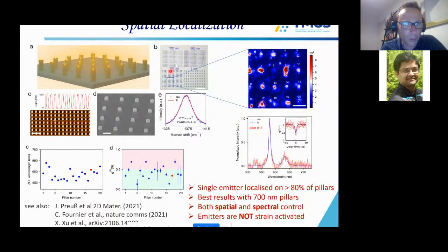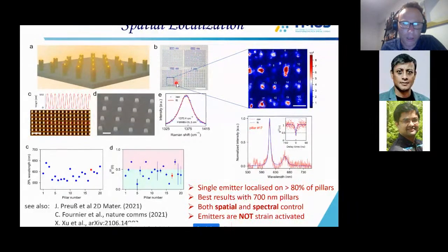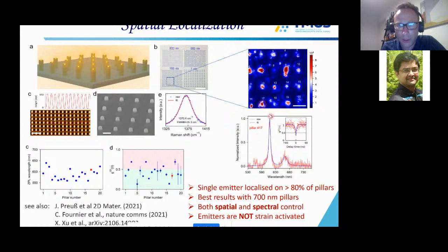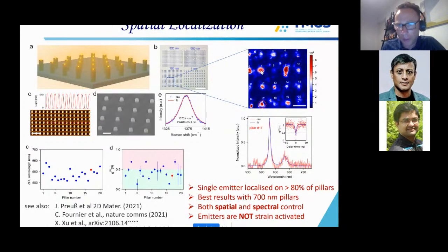And so we played around with the size variation, and you can see that basically for 700 nanometer pillars, you can get very nice emitters. So every pillar has an emitter, and most of them are also single. So you can see here this histogram of the g2 function as a function of pillar. And so this is nice not only because you have one emitter per pillar, but they're also bright, and you can actually go back to the same pillar location again and again if you want to do more measurements.